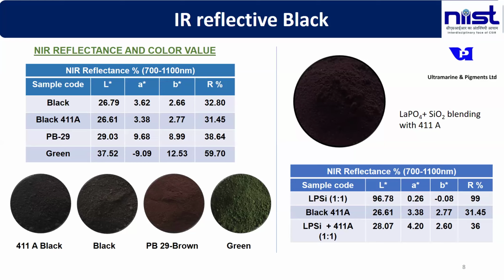We attended how to enhance the IR reflectance quality of the conventional black color. That was another next target. And we used our composite strategy. That composite strategy says that, as I mentioned before, blending of lanthanum phosphate with the conventional black color, we documented that the IR reflectance is increasing from 31% to 36%. As far as the dark color is concerned, whether it is a dark brown or dark black, even 1% improvement in the IR reflectance is a big matter.